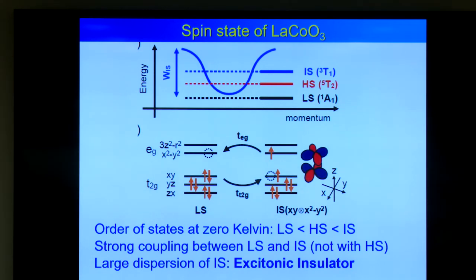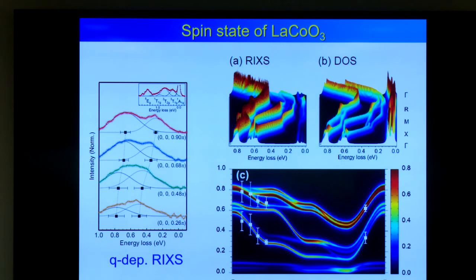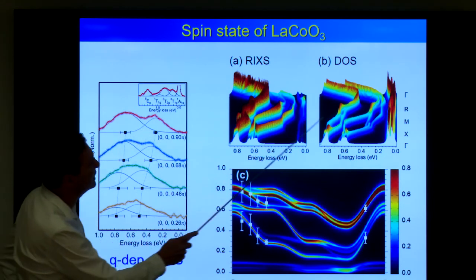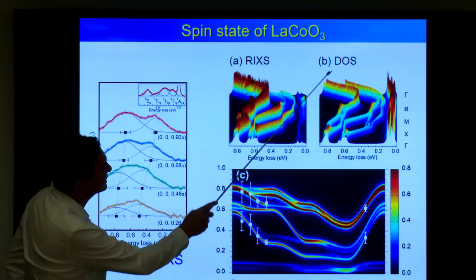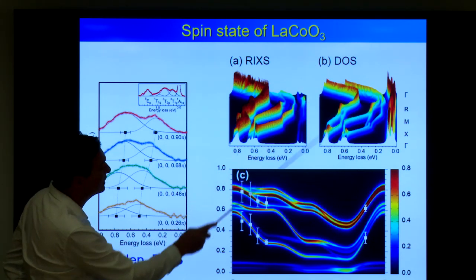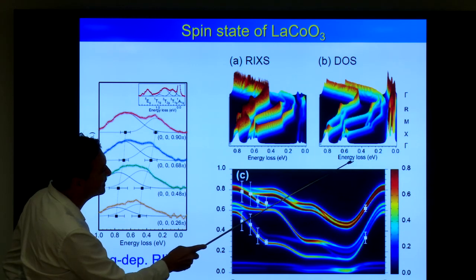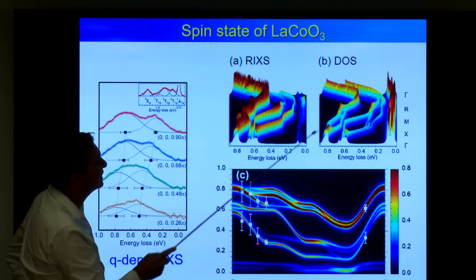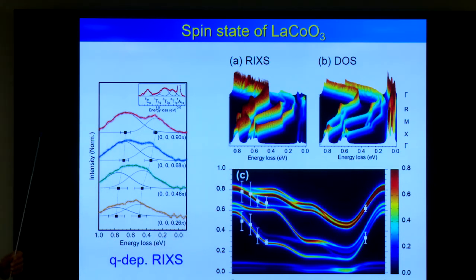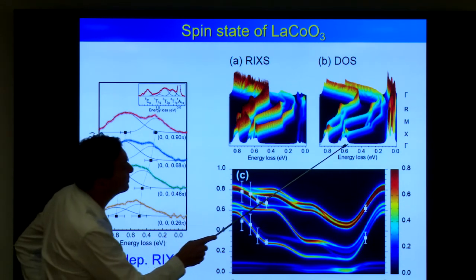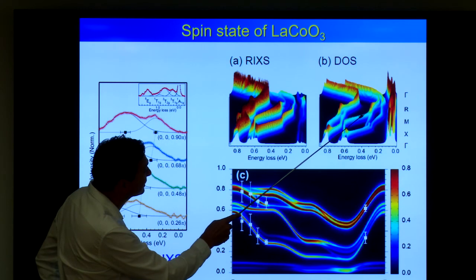But so we did some calculations. Actually, these are now calculations from Atsushi Hariki. So we analyzed the data. I will skip that part, but I will show this graph. This is the density of states of lanthanum cobalt oxide. But you see here energy loss. So this is not the normal density of states, but this is the density of electron-hole excitations as a function of momentum in the single crystal.